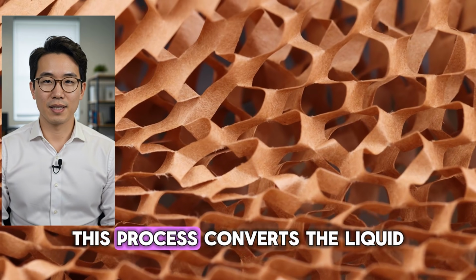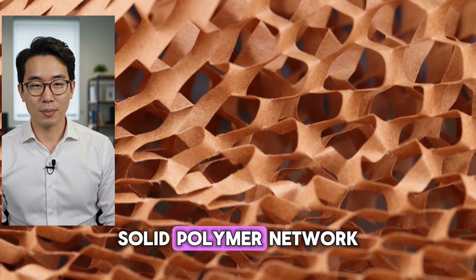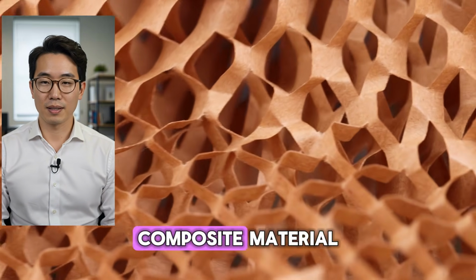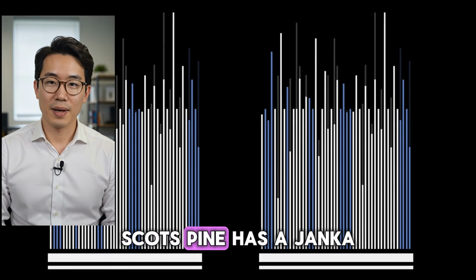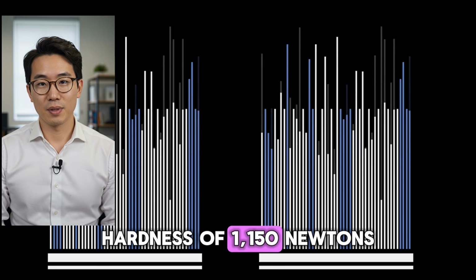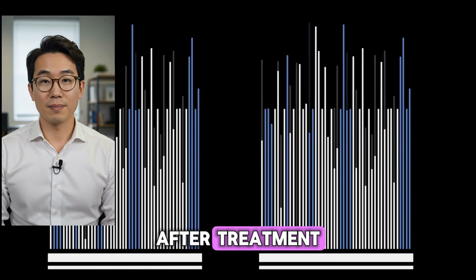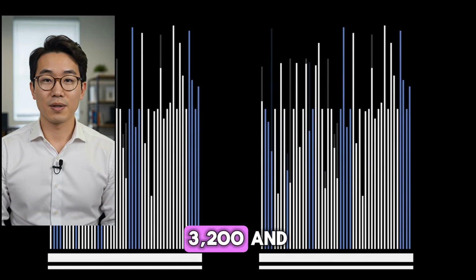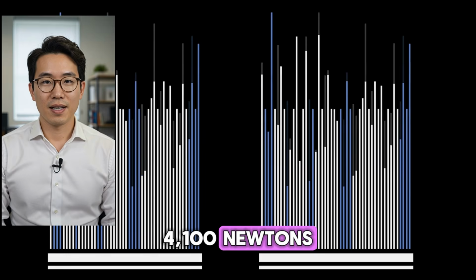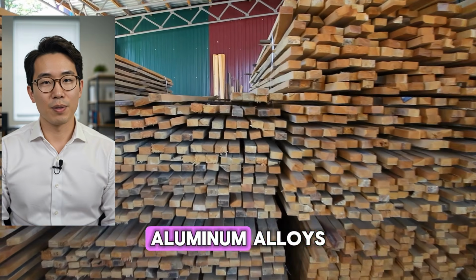This process converts the liquid resin into a solid polymer network. The wood becomes a natural composite material. Standard untreated Scots pine has a Janka hardness of 1,150 newtons. After treatment, it reaches values between 3,200 and 4,100 newtons. That is approaching the range of structural aluminum alloys.